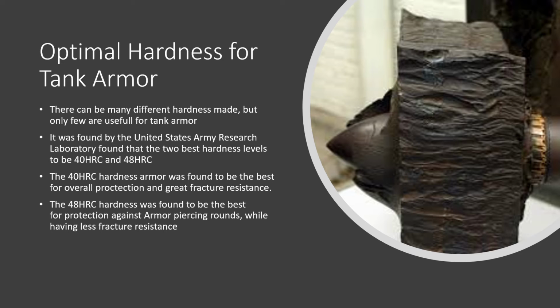The 40 HRC hardness was found to be best for overall protection and had great fracture resistance. The 48 HRC hardness was found to be best against armor-piercing rounds, but it gave up a little bit of its ductility and fracture resistance.